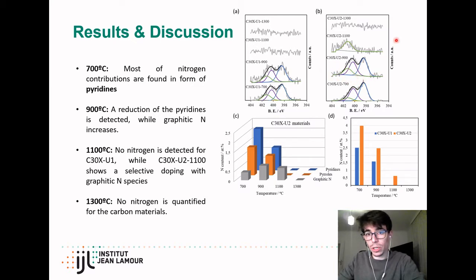And this is especially noteworthy at 1100 degrees, in which only one nitrogen species, only graphitic nitrogen, is observed in the nitrogen spectrum. All this trend can be clearly observed in the quantification of these peaks, since as we can see in figure C, it's possible to observe the decrease of the pyridine content and also the pyrrole content, while an increase of the graphitic content is observed by increasing the temperature of the heat treatment.